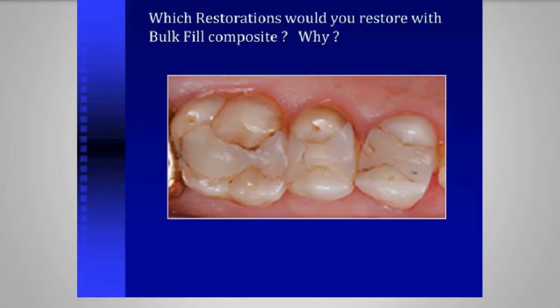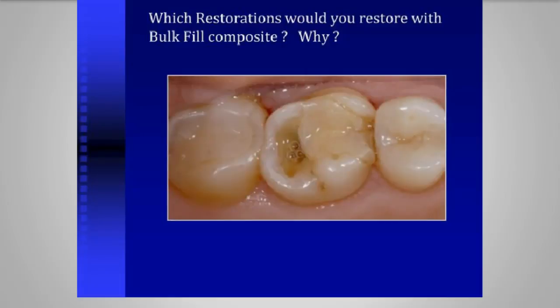When we get into this taking apart business, especially in the bicuspid here where we have weak buccolingual cusps, well, we're not calling them composite restorations. These are actually core buildups, and you can use the bulk fills for core buildups, and you can use the dual cure bulk fill Fill-Up from Coltene as a core buildup material. There's just too much potential stress, too much core weakness to leverage incremental layering in there, at least in my standards that I apply in my practice.